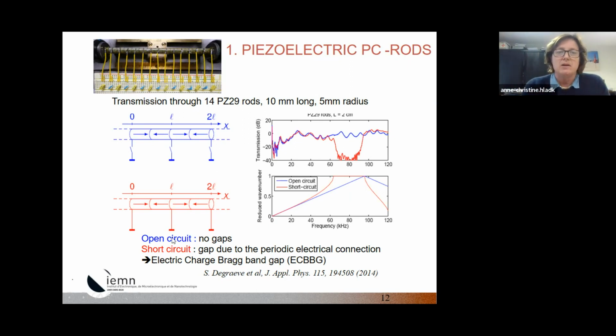Then we apply the electrodes in short circuit, and in that case, we see a drop in the transmission that corresponds to the electric charge Bragg band gap. Here you have the dispersion curve. So here is the experimental evidence of the electric charge Bragg band gap.